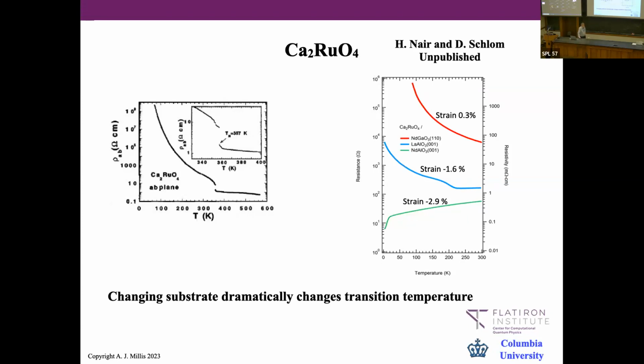Now this transition is remarkably sensitive to all kinds of perturbations. In particular, in very interesting work that Harry Nair, who was a student of Darrell Schlom and has now moved on, did, and for reasons I totally fail to understand, never published, they showed that the transition was extremely sensitively dependent on what substrate you grew the material on. Growing the material on different substrates, basically, if you like, applies a strain.